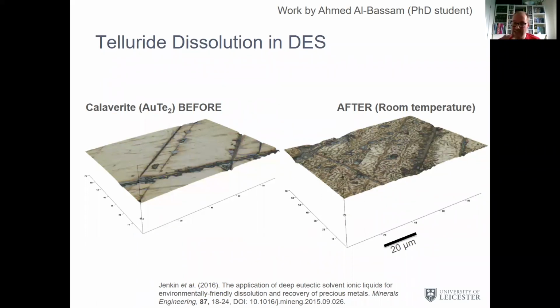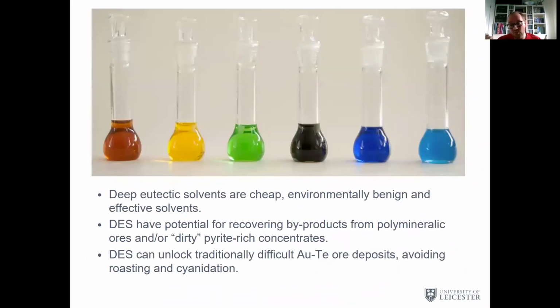So slightly less soluble than the gold. So we're seeing an etching effect here rather than a full dissolution after the timing of this experiment. But it's showing promise, better than cyanide would do for calaverite. Basically, calaverite would be more or less insoluble in that solution. So we think we're onto something here, and it's an ongoing piece of work and something that we are continuing to look for partnerships and collaborations for.